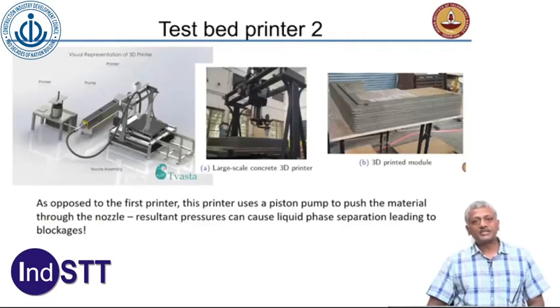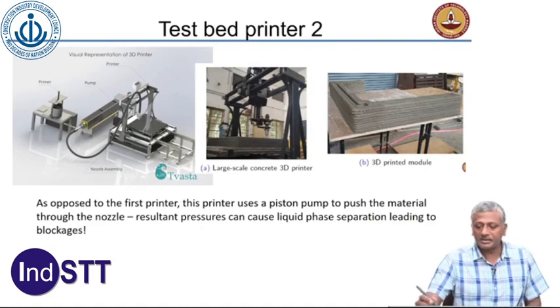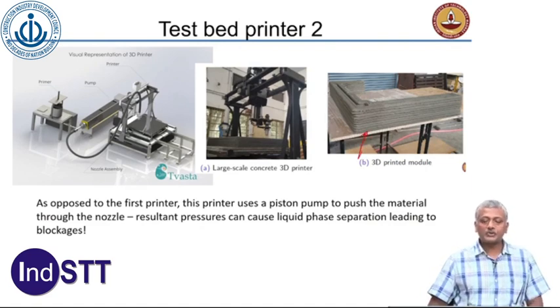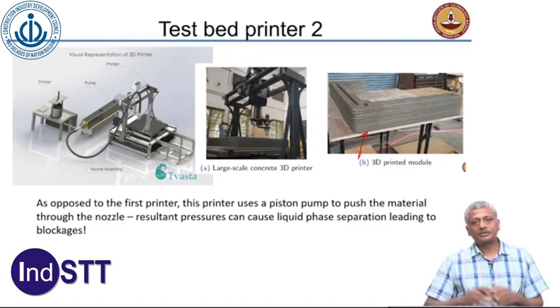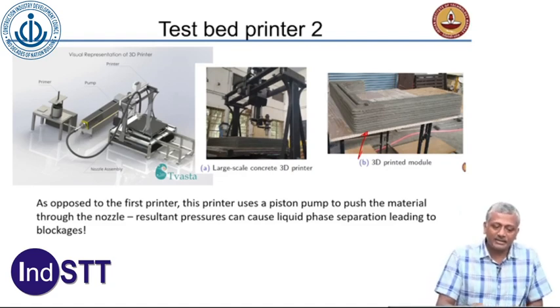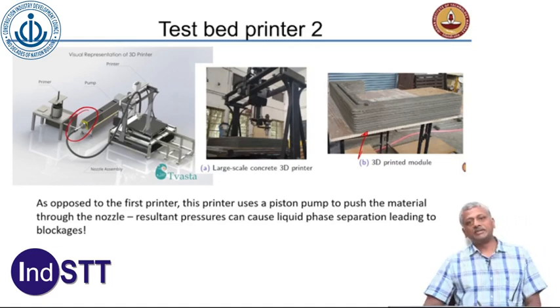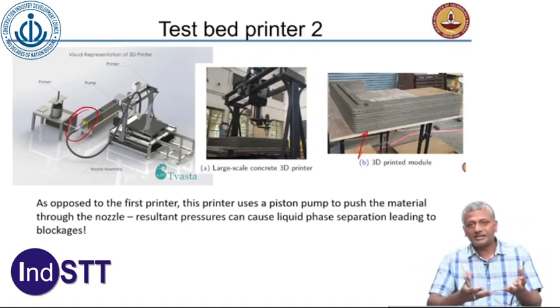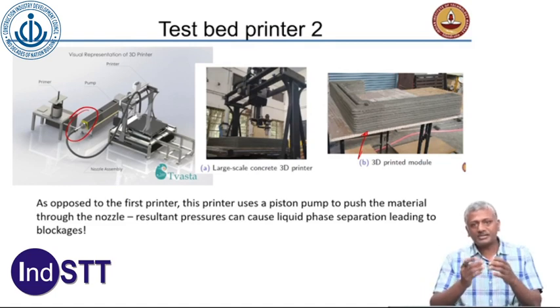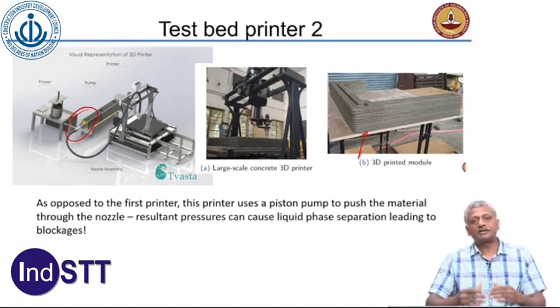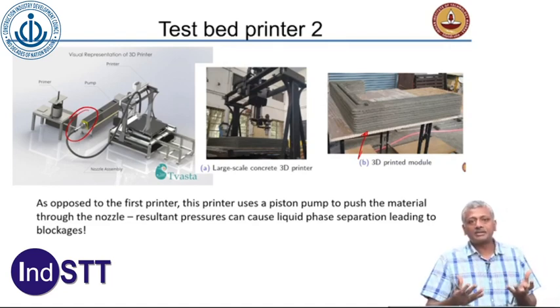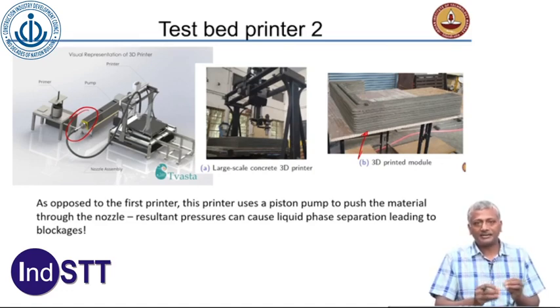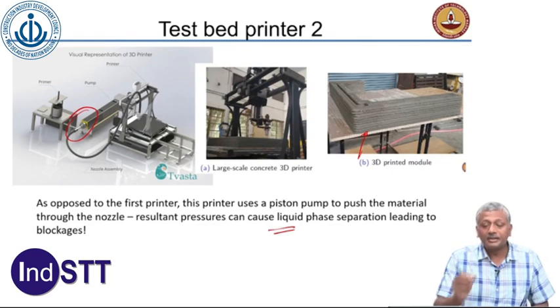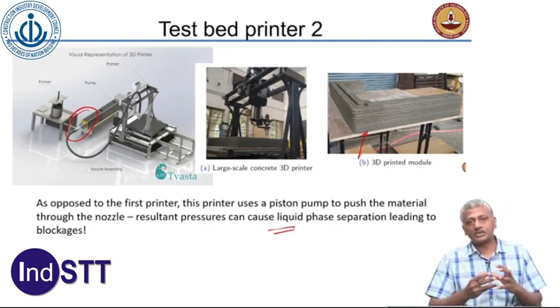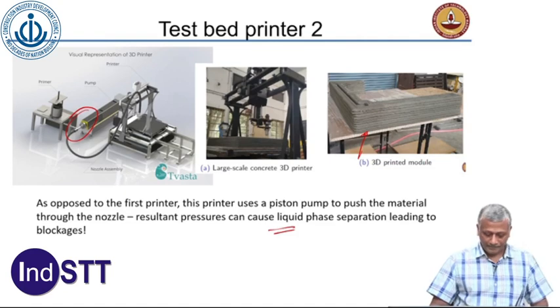So the testbed printer 2, which I said was still a research based printer, was used to print these sorts of modules, and these modules were then stacked together to form a larger room shaped structure. The one difference here was that the mechanism of delivering the concrete was through a pump. So we are actually pushing the concrete, the advantage being that we can now start pushing very stiff concretes through the nozzle, and stiffer concretes are better from the view of buildability. They can build up quite nicely. Problem is the pressure that you apply may cause a phase separation of the liquid from the solid, and that is something that you need to accommodate for by choosing the right type of testing mechanisms to ensure that you don't cause this phase separation.